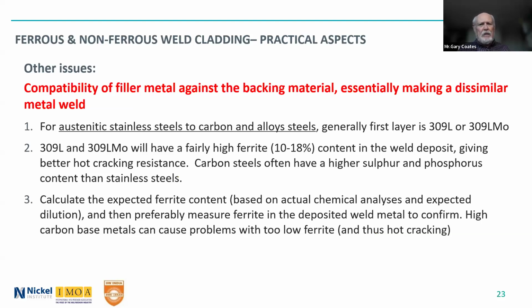So the compatibility of the filler metal against the backing material, essentially it's a dissimilar metal weld: austenitic stainless steels to carbon and alloy steels. You generally use 309L or 309LMo, depending on whether you want the molybdenum there. Occasionally, you might use a nickel alloy for that, even if you want a stainless steel there, because the nickel alloy does not form that martensitic layer usually.